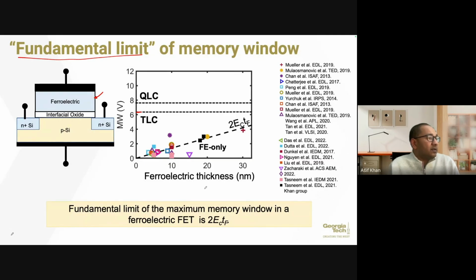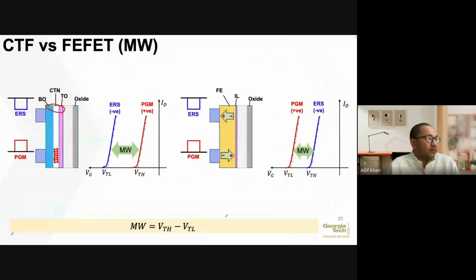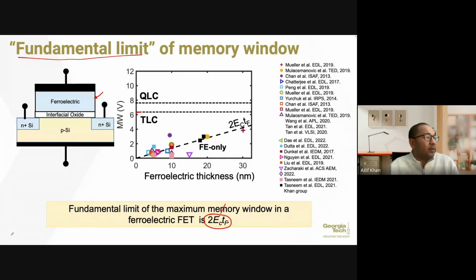Now, in general, in a ferroelectric field effect transistor, there is a well-known limit of memory window, which is basically 2 times the coercive field times the thickness. In general, ferroelectric materials have a coercive field of 1 megavolt per centimeter. So to get a larger memory window, we need a larger ferroelectric thickness. But whenever we plugged in this number of 1 megavolt per centimeter, we saw that none of the existing data actually allows us to get a 6.5 volt memory window for a thickness range of 20 nanometers. So that was the limit that we were working against. And our team really needed to be innovative to design the ferroelectric material or the gate stack to get to this limit. And this was truly the genius of Dipjyoti, who really showed that with ferroelectrics you can reach this limit. That's the story I'm going to tell you in the next 5 or 6 slides.